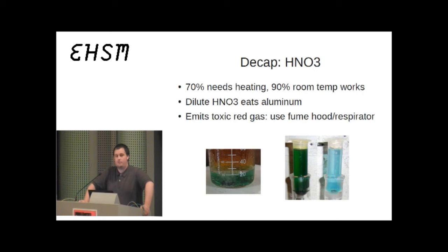But I know some people, what they'll do, and I've done this before, is just throw a chip in a little vial of it, and come back a few hours later, or even a day, depending on the size of the chip, and it'll be decapped. You didn't need to have any heat, and it'll put off a lot less fumes. But you do have to be a little careful, especially if you're using the lower concentrations with heat, because as the acid eats the epoxy, it's going to lower in concentration. And this will have a tendency to actually corrode the chip more than when it was at a higher concentration.